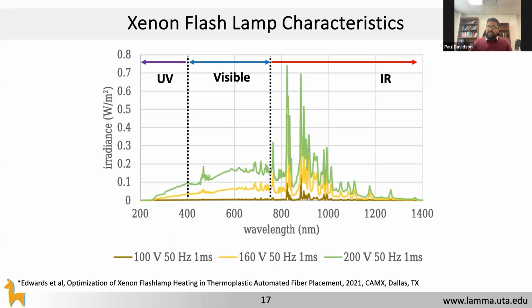And that is important for us because unlike laser systems where you have a very narrow range of infrared heating, this is the spectrum of the flash lamp itself. So you can see we have some amount of ultraviolet, the full spectrum of visible range, and a very broad spectrum of the near infrared. So unlike laser, where you typically operate at 980 or 950 nanometer scale, we have everything from 700 to 1200, right? So we needed to know how this broadband spectrum influences the heating in our tape material system. Not only that, depending on your pulse parameters, you can get very different irradiation levels.